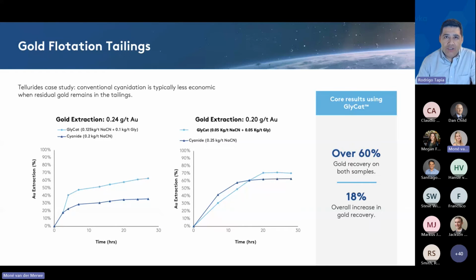Let's see two scenarios with different gold grades. The first one, the left side, in a sample with a gold grade of 0.24 grams per ton, glycat increased gold recovery to 62% from 35% while using less cyanide. The second one, the right side, in a sample with a gold grade of 0.2 grams per ton, a reduced glycat formulation also achieved a 62% recovery. Glycat resulted in over 60% gold recovery in both cases, highlighting its efficiency even with lower reagent levels.